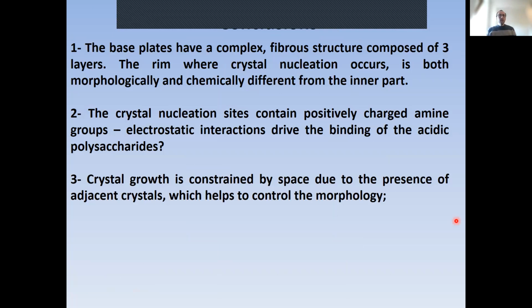So I'm going to conclude. The main things that we learn is that, first of all, the base plates have these very complex structures that are composed of 3 layers. We have the rim where crystal nucleation occurs, which is morphologically and chemically different from the inner part. And the difference in chemistry is this functionalization with positively charged amine groups that form binding sites for the polysaccharides to bring calcium ions. In terms of crystal growth, we can see that it's constrained by space due to the presence of adjacent crystals, and of course that is going to form an important mechanism to control morphology.